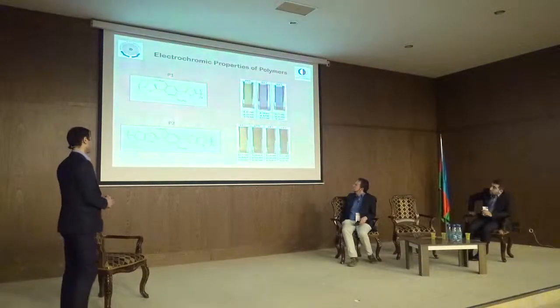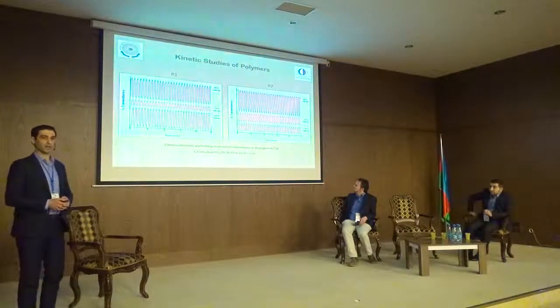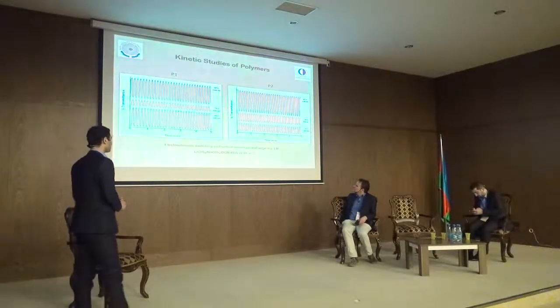Here you can see the color change of my polymers. Both of my polymers were multichromic, and they changed colors from yellow to blue, but the second polymer also exhibited a green color in the intermediate state. Kinetic studies of both polymers were conducted in order to determine switching times and percent transmittance changes. Switching time is the time required for switching between two extreme states of the polymer. For the first polymer, switching time is one second at 490 nm, and for the second polymer, the minimum switching time is 0.2 seconds at 608 nm.